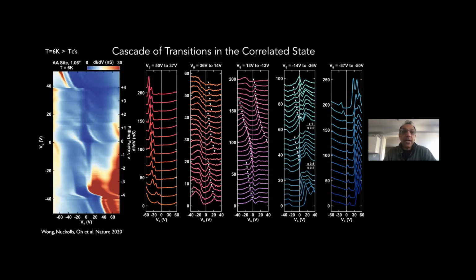So now we look a little bit more carefully at these blurry regions, and you can start to see that there are sharper features within this region of partial filling, and you can mark it by whether you have 4 electrons or 3 electrons per Moiré unit cell, or 0, which is charge neutrality, and whether you're putting holes there. I'm sorry, this is up to 8 electrons. This is 4 electrons, and this is no electrons, which is where you have -4. So you can see this succession of features that are happening every quarter filling in the system.